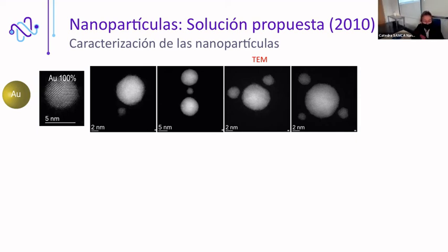I have also one general question. It's about this collection step, because, for example, in this case, the collection chamber is always under vacuum. So it seems like the nanoparticles impact the surface, and then you collect, then you sweep, and then you go to the TEM to analyze the structure. And how difficult is it, I mean, how is the yield, the efficiency of your process? Because here we have an experimental setup for laser pyrolysis, and the yield is almost very low. When we have to clean and so on, everything is spread on the walls, and this is like the main bottleneck of the technology.